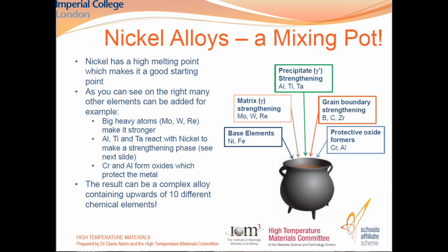Nickel alloys are very, very carefully controlled. So we tend to pick elements off the periodic table and add them in the right amount, and they have been studied for so long in order to achieve the desired mix of properties. So nickel has a high melting point, which is a good start, but all these other elements like aluminium, titanium and tantalum, molybdenum, tungsten, rhenium, iron, boron, carbon, zirconium, chromium and aluminium are added for specific reasons. So we need to add some big heavy atoms to make it stronger. We need to add some things that produce the strengthening phase that I'll explain a bit more about later. And chromium and aluminium are added for protection. And then I'll also explain what grain boundaries are and why we need to strengthen them. The result is a very complex alloy that contains 10, 14 elements, each serving a very specific purpose.